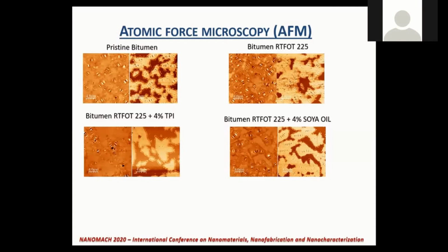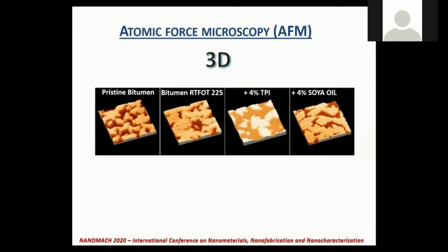In the images relating to the samples with the addition of the regenerating additive TPI, an increase in the soft part is observed, and these images are very similar to those obtained for non-aged bitumen. Samples with soy oil instead show very similar images to those recorded for aged bitumen. This effect is more evident in 3D figures. We can therefore say that even this technique allows us to distinguish the regenerating effect from the fluxing effect.